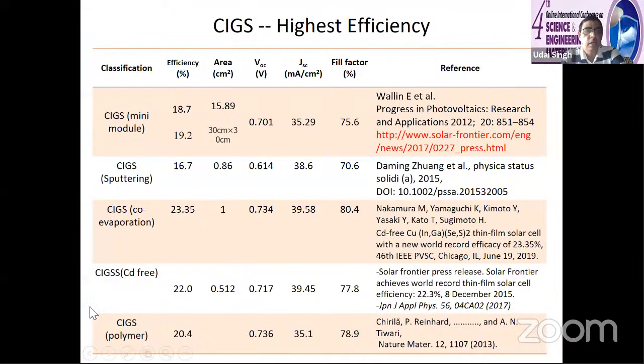is the highest. Like if you go to the Japanese, this is a P-type material, then you have to make a PN junction, you use the cadmium sulfide. But the Japanese don't use cadmium as it is toxic, so they use cadmium-free materials. They have achieved around 22%. On the polymer substrate, that is the flexible polyimide substrate, the highest efficiency achieved is around 20.4. So you can have different processes and different materials you can use.